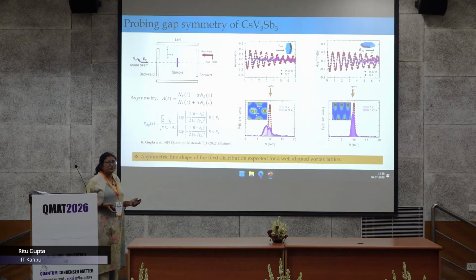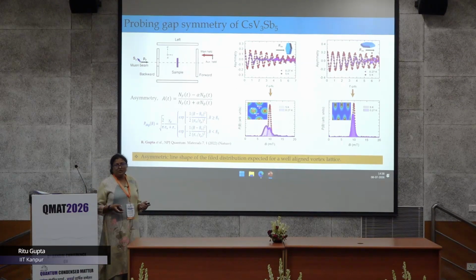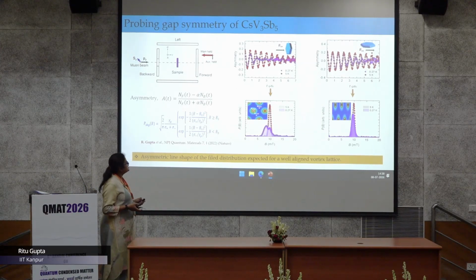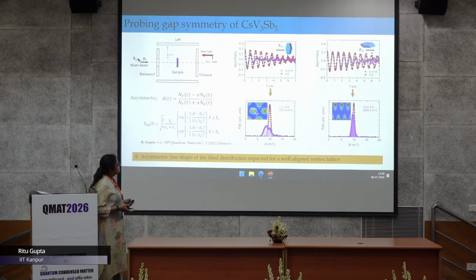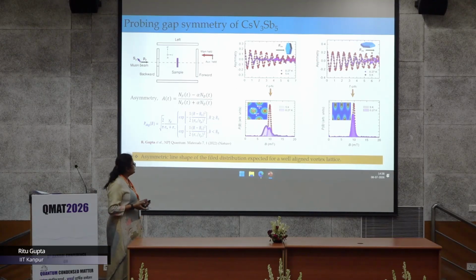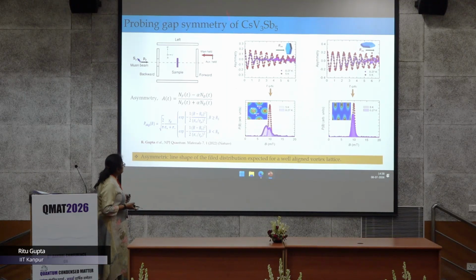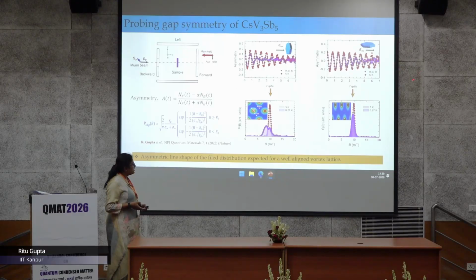This is because of the inhomogeneous field created due to the vortex formation, and the same goes for B external parallel to the Kagome plane. And if we take the Fourier spectra, you see this is the 5K one. Of course, you should see a peak, but as I explained, there is nuclear magnetic moment present in the system. But if you look in the superconducting state, this spectra is rather asymmetric in nature. So this shows that the crystals are of good quality.